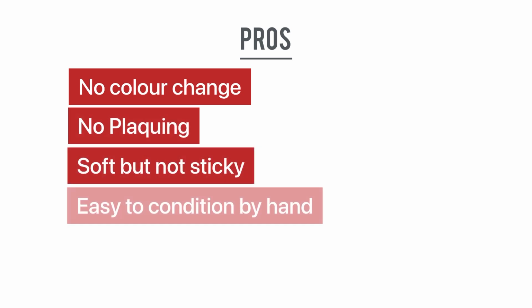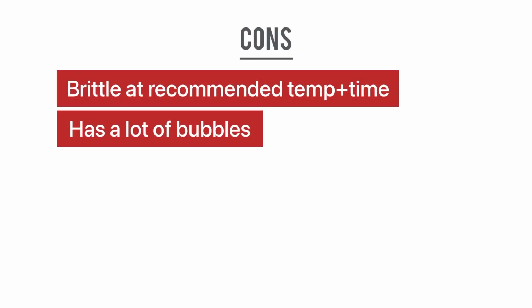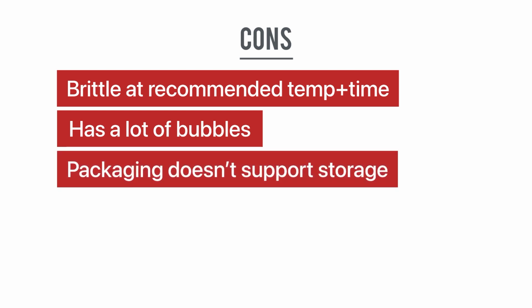Let's revisit the pros of this variant. I'm quite pleased with the opacity and the color of this particular variant. It doesn't change on baking, no plaquing, great consistency to work with, and no need for leaching either. Now the cons of this variant: the strength is definitely an issue and it might require a longer bake time to fix that. It has a lot of bubbles upon baking, so avoid using this for flat surfaces or bake it sandwiched between tiles or slabs. I'm also not a fan of the packaging, which could be a little better in my opinion.